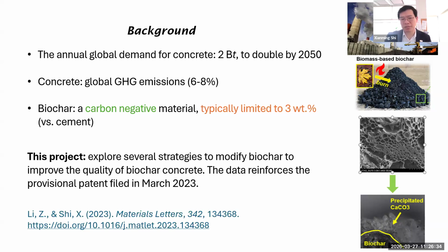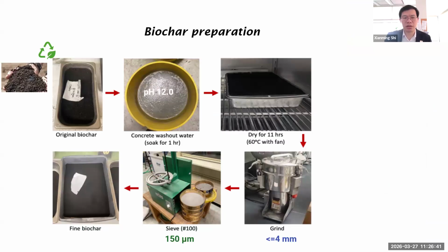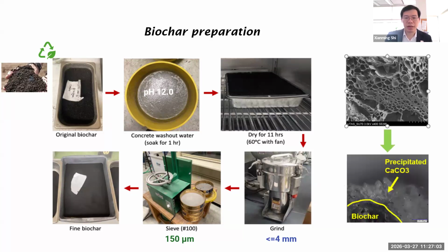So we published a proof of concept paper in March 2023. Here's a study where we first start from this cow manure derived biochar. As you can see, we used concrete washout water, which is another waste stream from concrete production, and it has a relatively high pH around, say, 12.0. You can see we dry it, then we grind it, we sieve it. The purpose of using the washout water is because it has not just the high pH, but also calcium cations in it. CO2 from air would react with these calcium cations and precipitate nano or submicron size calcium carbonate on the surface, as shown here under the scanning electron microscope.